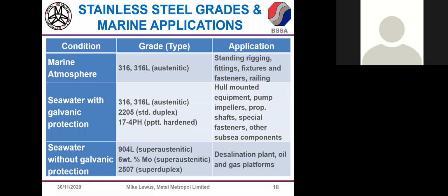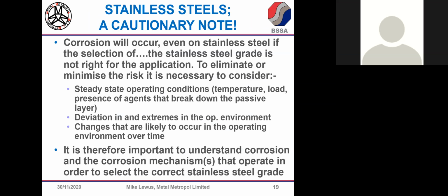17-4 PH, a precipitation hardened martensitic grade, has less corrosion resistance than any of those in that middle list, so it's not surprising that it needs protection. But there are grades that can survive seawater conditions without any protection. There's 2 categories essentially: the super austenitics and the super duplex grades. Again, I'll say more when we get onto the corrosion why those are particularly useful if you want to make something that doesn't need any protection.